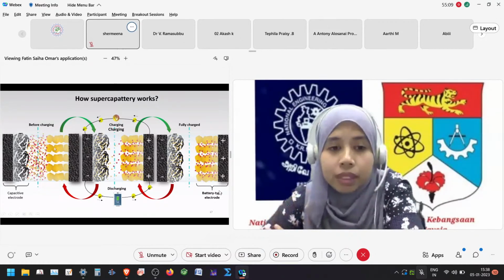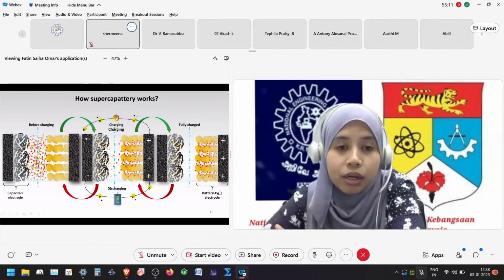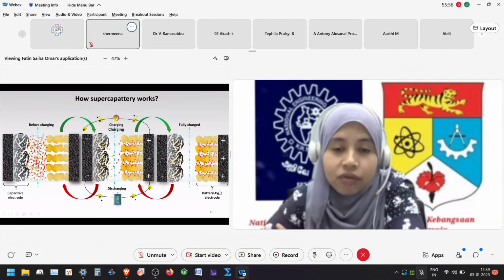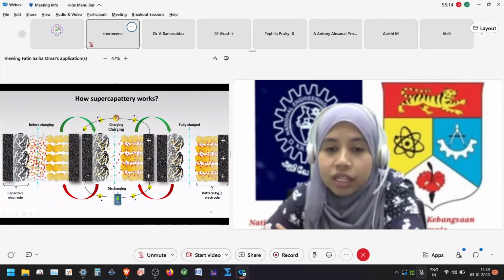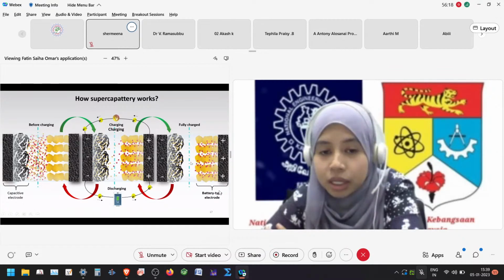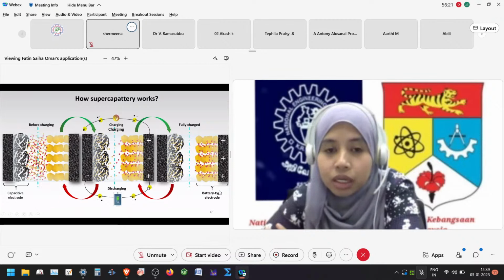So the electrode with the carbon-based material is negative, and the electrode coated with the battery material is positive. Because of the oxidation, a reaction happens when the negative ion of the electrolyte interacts with the positive electrode, until all of the electrolyte ions are separated. And during discharging, the electrolyte ions will leave the electrode, and then go back to the bulk electrolyte.